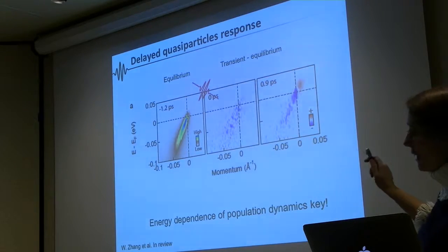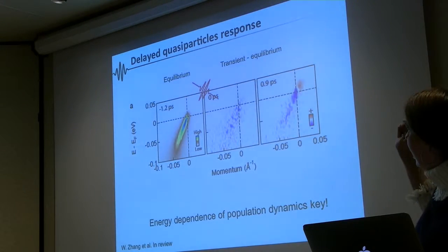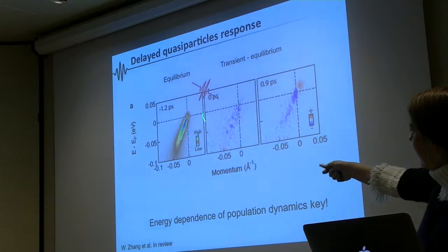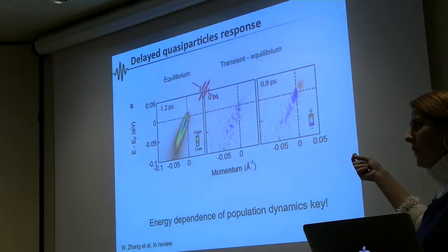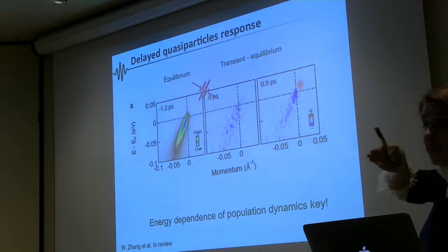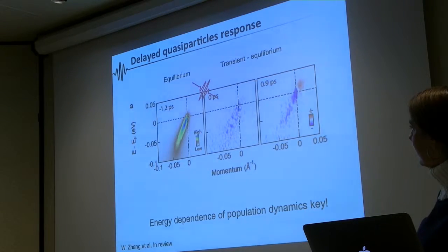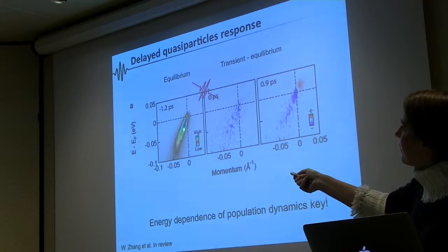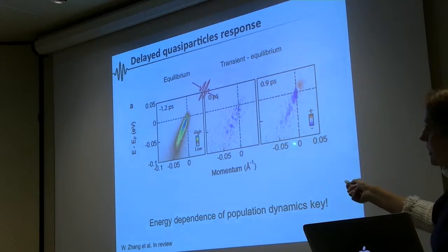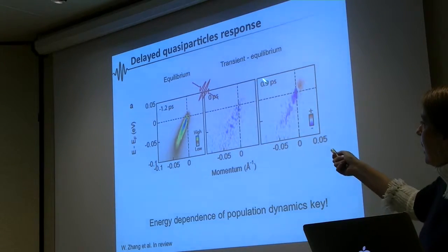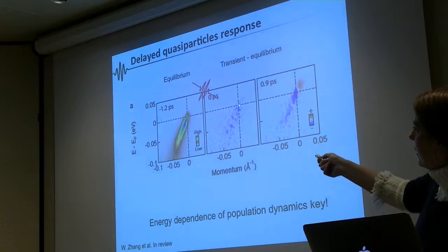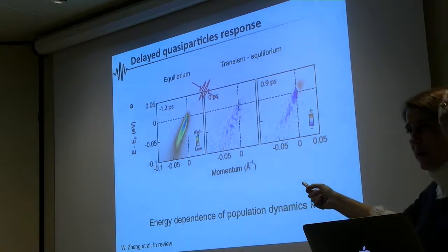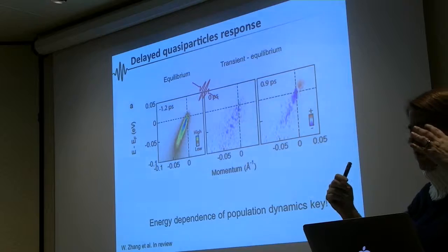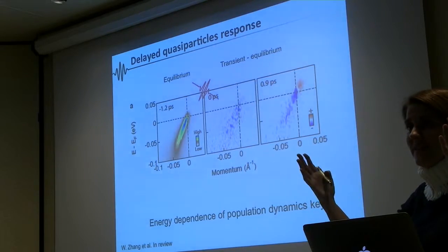So, last thing, and then I let you go. One interesting thing is that I told you at the beginning that everything seems to respond within this energy scale, which is the phonon energy scale. These are different spectra, so they look a little bit noisier. But the interesting thing is that when you look at the phonon energy scale, you have exactly the same phenomenon. Pretty much at t equals 0, here I'm showing the difference between equilibrium and normal state, between equilibrium and transient state.